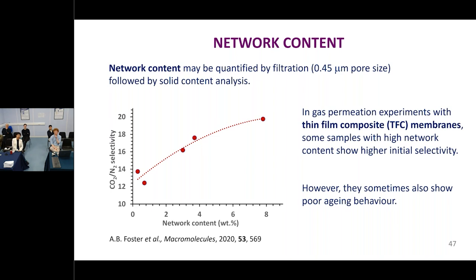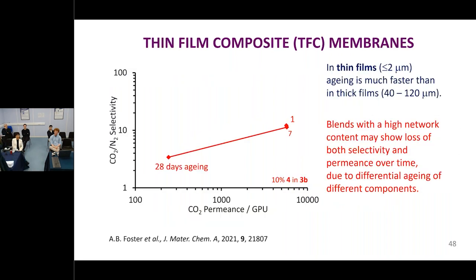And at first we thought we wanted network because we can actually improve selectivity. But then, particularly when we're thinking about thin films, which I said are very different to thick films, sometimes we then get really bad aging behavior. So we think we've got an advantage in the short term. The student goes back a few months later and it's a disaster.